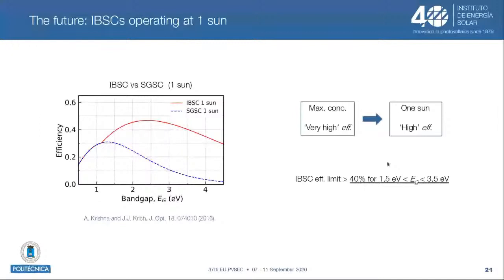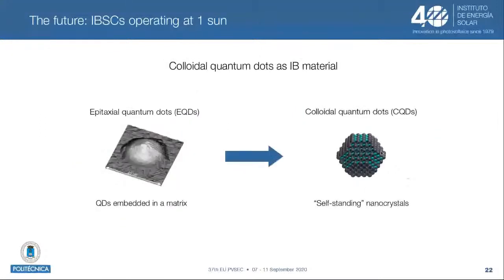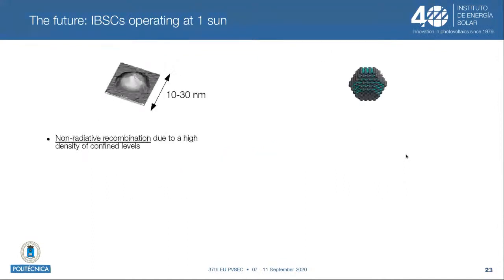But between this large variety of materials that we can explore, in this presentation we will focus on one technology, which is colloidal quantum dots. So we propose a shift from the epitaxial quantum dots, which provided a very good demonstration of the intermediate band principles, to colloidal quantum dots, which I call here self-standing nanocrystals, to differentiate them from the epitaxial quantum dots in the sense that they do not have a surrounding material. So they are just self-standing. And we think that these colloidal quantum dots are a technology that can overcome all the shortcomings of epitaxial quantum dots. And I will tell you now why.